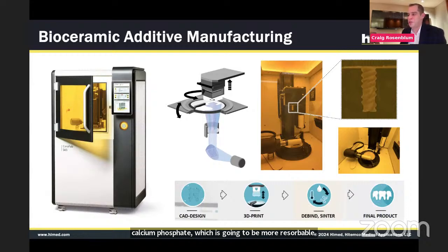In fact, Lithoz, they just released a dual-headed printer, and you have the ability to print with multiple materials. Currently, when I describe biphasic calcium phosphate, say 70-30%, I'm talking about, say, taking 70% HA, 30% of beta TCP, mix them up, and then you have one homogeneous solution. But now the idea of being able to have two separate vats with two printer heads, and to more clearly define what everyone is looking at, this is the print stage, and it dips inside of this vat.